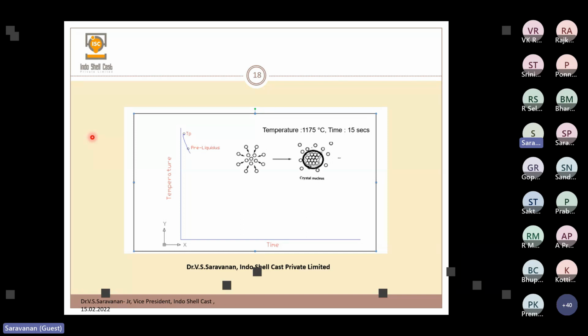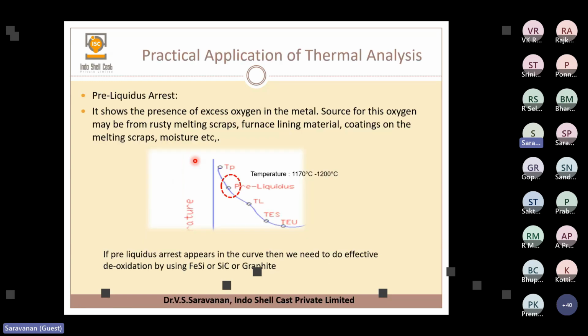So there the temperature remains the same, but this particular point, the pre-liquidus arrest point, is not a permanent one. Once the small amount of nuclei is formed everywhere, the latent heat liberation will take place, and then again the temperature of the metal will go up a little bit, and then again it will dissolve. Or otherwise, what happens? At this arrest point, this pre-liquidus, even without the temperature increase, because of the latent heat, the existing temperature is just sufficient to dissolve the nuclei. So the nuclei formed here will dissolve.